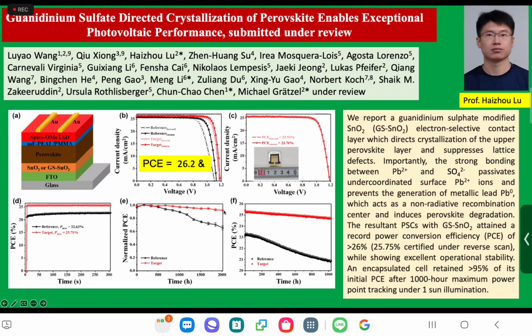This is very similar to what I just showed you, but this time for an NIP structure. And so it's wrong to say NIP structures are less stable than PIN. If you have that opinion, I recommend you to read Anders Hagfeldt's paper that just came out in Nature Energy. It shows 4,000 hours stability for NIP. Well, that's for MPP tracking, and 1% is the error limit degradation. Okay, so back to our work.